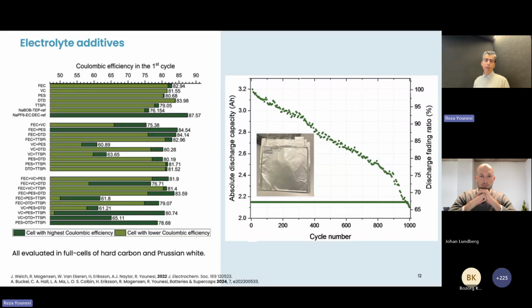A common practice is that you try to make the SEI formation more efficient when the electrolyte itself is not very efficient at forming SEI. So here we have evaluated a number of different additives, and what you see on the right is that we have enabled sodium BOB in TEP electrolyte to cycle for almost 1,000 cycles with 65% capacity retention. And these are multi-layer cells based on Prussian white and hard carbon that we have evaluated here.